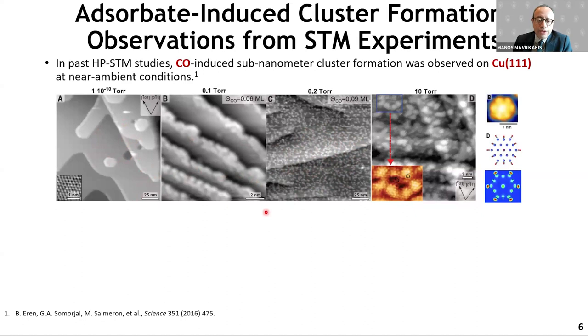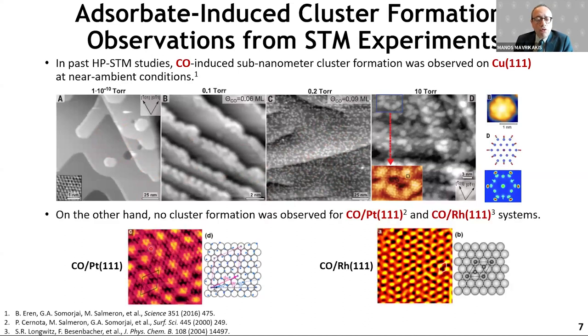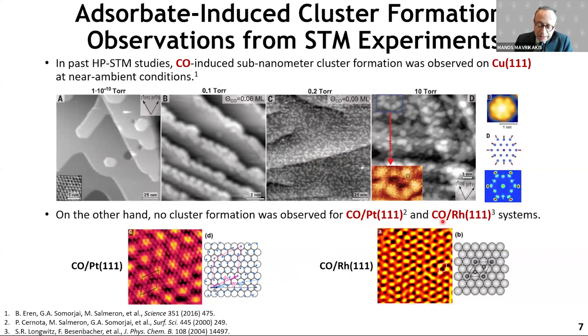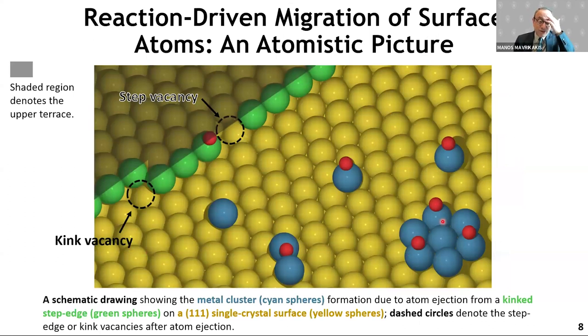Another question that's interesting to pose here is, this is a very specific system, CO on copper. What happens if you go, say, to CO on platinum, CO on rhodium? Well, it turns out the same method, similar conditions, they couldn't find any cluster formation. So why is that the case? And what would happen if we go to other reactive species beyond carbon monoxide, which is a very common reactive intermediate for catalytic transformations? So to start out discussing the theoretical and computational network framework that we developed to understand this,